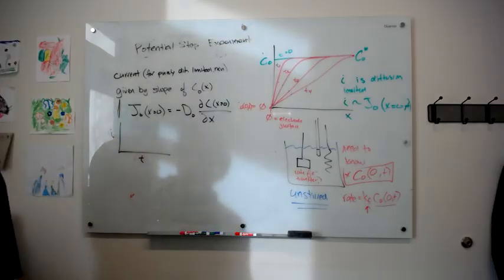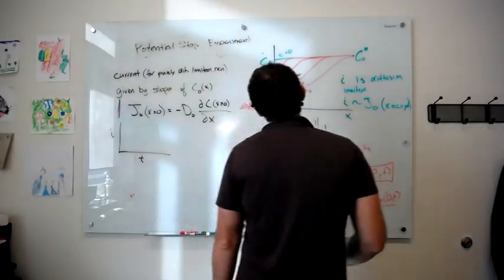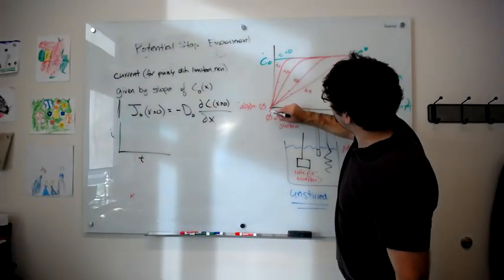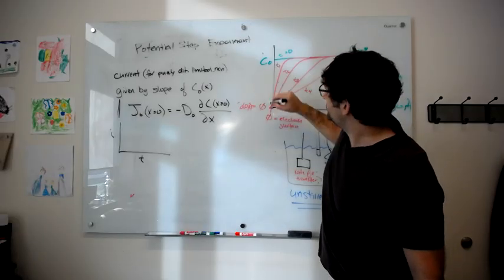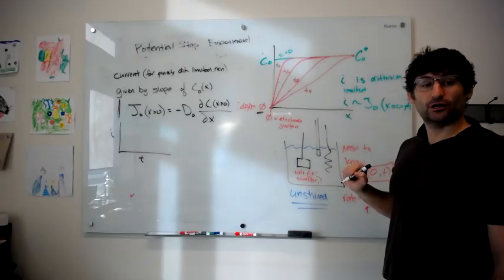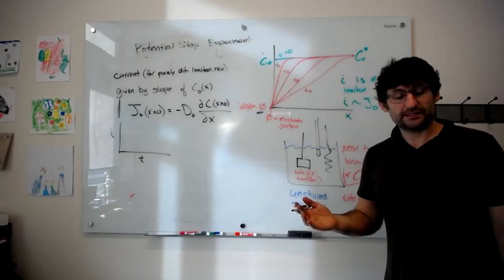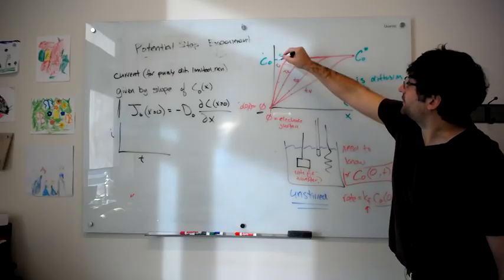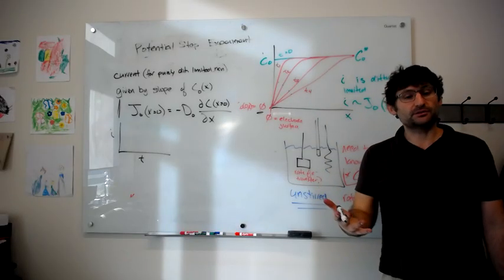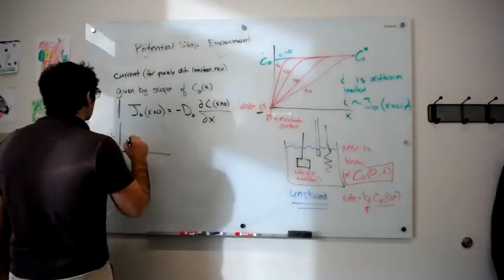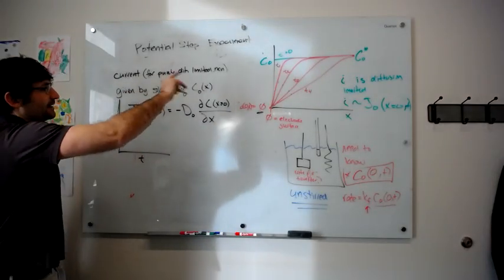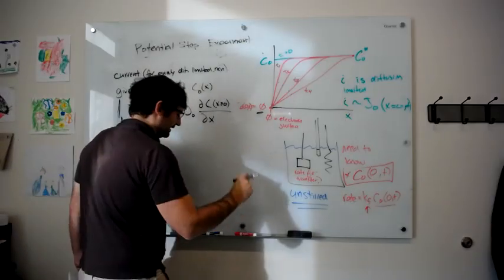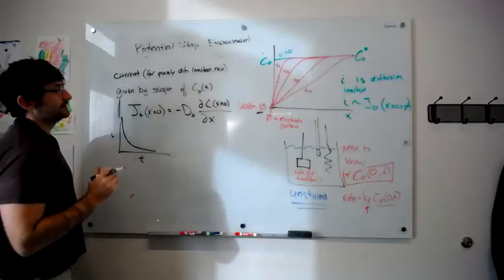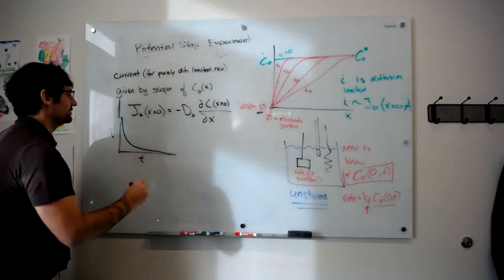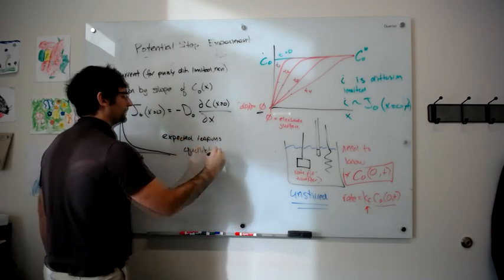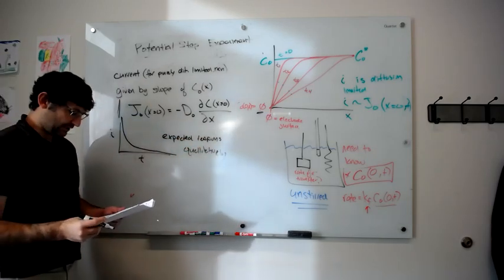So if I plot the current from this system as a function of time, when's the current the largest? Well, at time equals 0, what is the slope going to look like? Imagine I immediately set the surface potential of the electrode such that the surface concentration of O is 0. All the O that is there is immediately reduced to R. Well, I'm going to have essentially a step function in concentration. So in fact, the slope, in principle, will be infinite. So the formal solution will find the current will actually go to infinity at time equals 0. And as time progresses, the current decays. And for long enough times, this concentration profile will get so shallow that the current will go to zero.